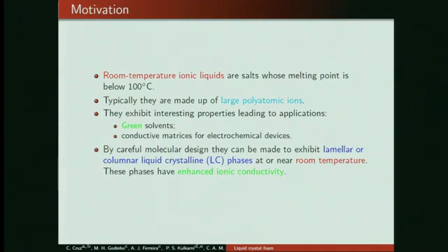Right, so at this point these friends were playing with room temperature ionic liquids, although I don't really think the results I'm going to show you are crucially dependent on the fact they're ionic liquids. What is crucial here is that these are room temperature ionic liquids which have some liquid crystalline phases. They are crystals at low temperatures; around either 50 or 70 degrees, depending on exactly which compound they use, they go smectic, and at higher still temperatures but below 100 degrees C they go isotropic liquids.